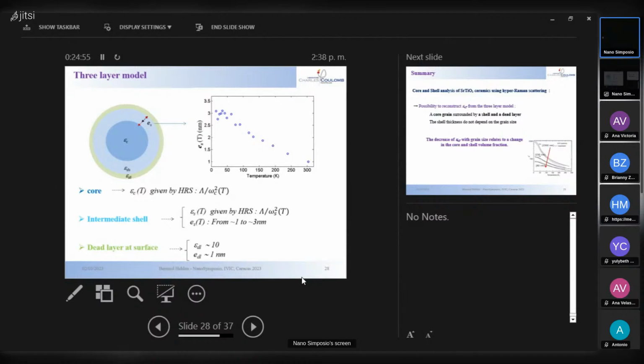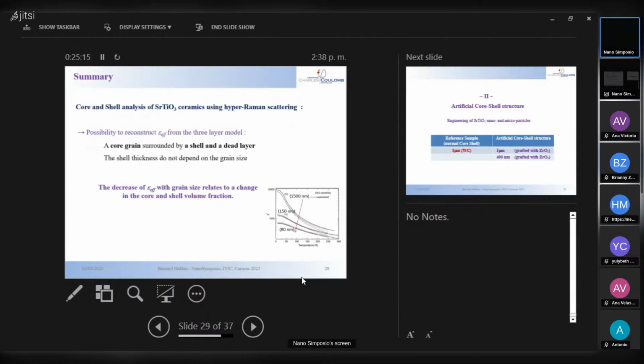We have the permittivity of the core, we have the permittivity of the shell, we have the thickness of the shell from 1 to 3 nanometers, and we have the permittivity of the dead layer and the thickness of the dead layer. So we have all this information, all included in our optical spectroscopic measurements.